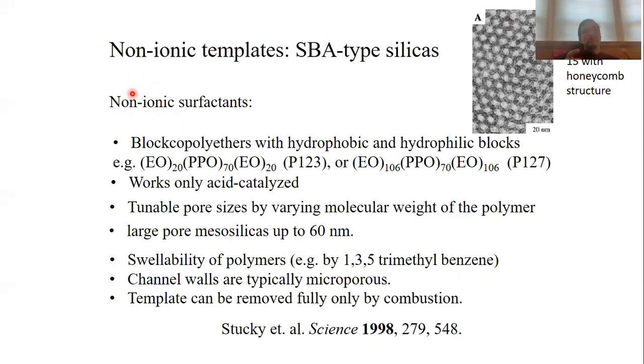Okay, so that after you remove that polymer by combustion, you're creating actually small micropores within the pore walls. Okay, so that's not the case in the case of the ionic surfactants.